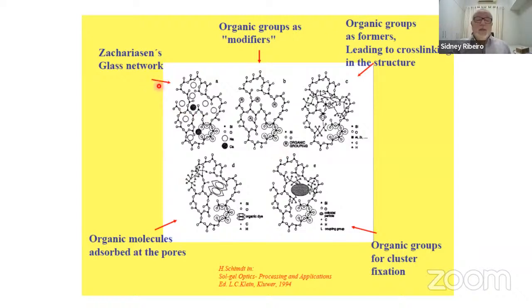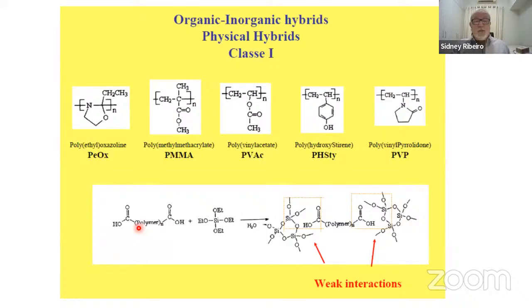There they play different roles in the structure. So in these materials, this is the so-called Zachariasen glass network, and organic groups can play different roles in the structure. They can play the role of network formers, for example, leading to cross-linking. They can play the role of fixation of clusters. They can play the role of adsorbents at the pores. A lot of different roles can be played by the organic parts. In general, they are divided into two types: Class 1, where you have polymer mixed with the inorganic material. So there are weak interactions between the organic and inorganic parts.